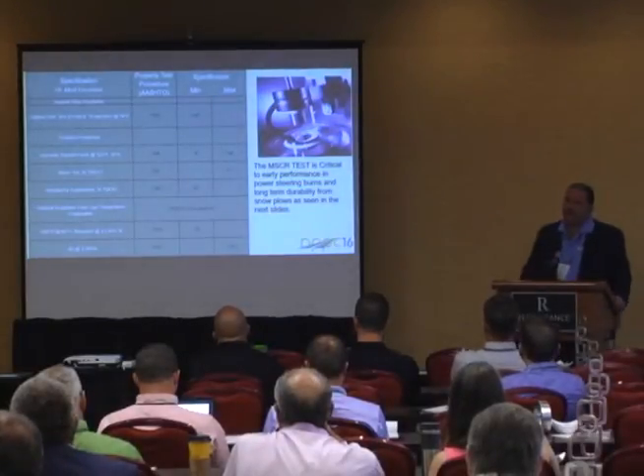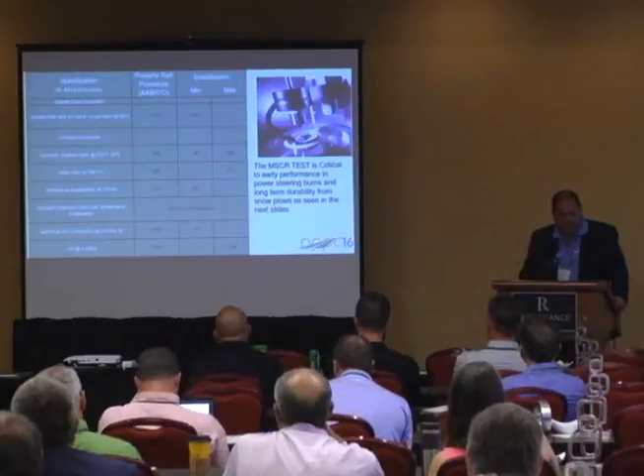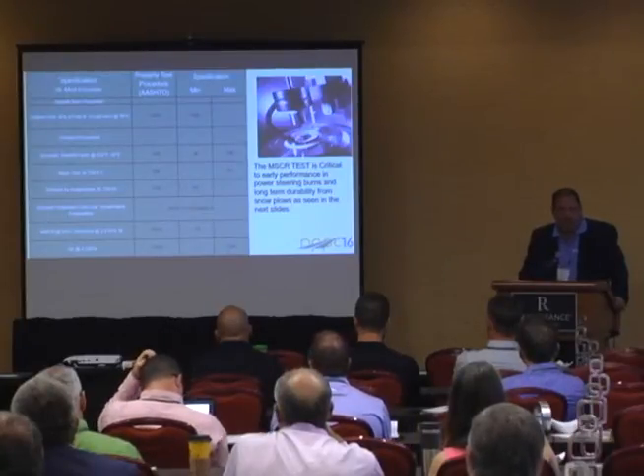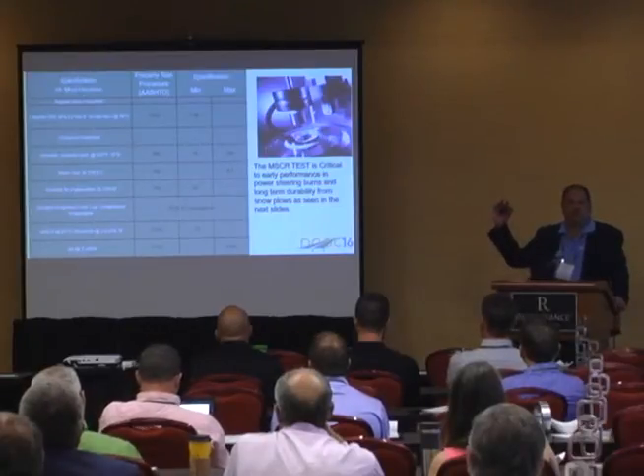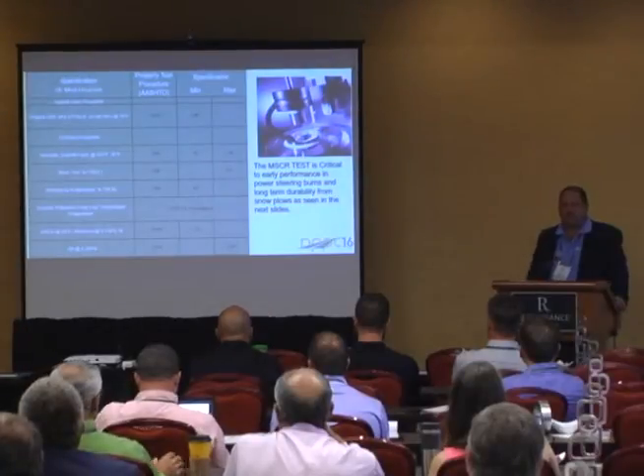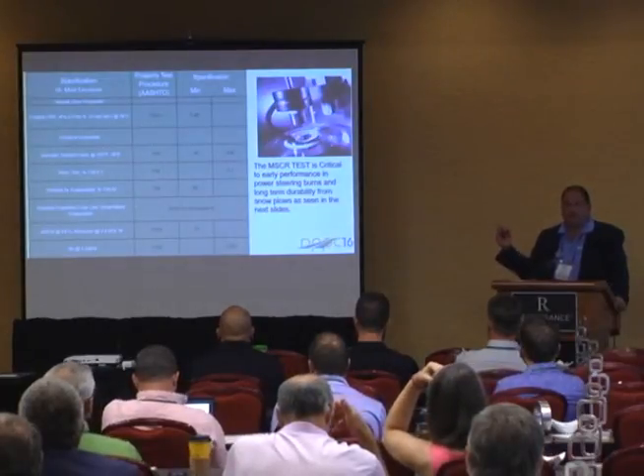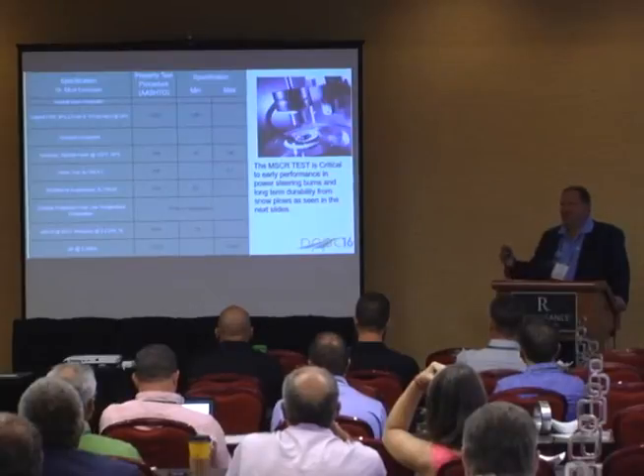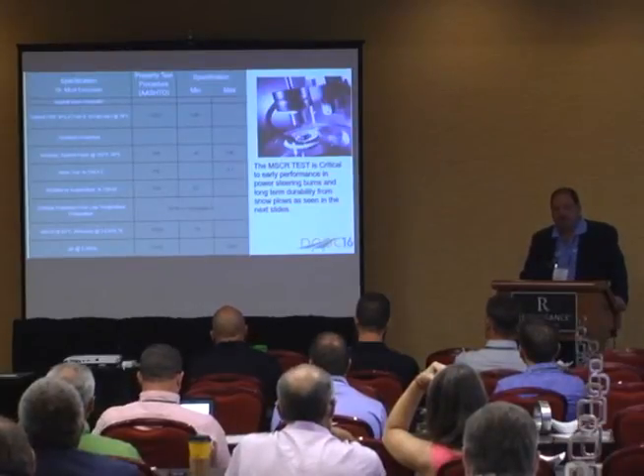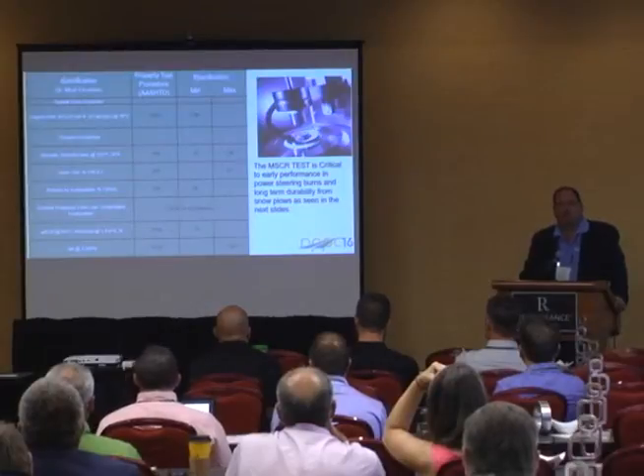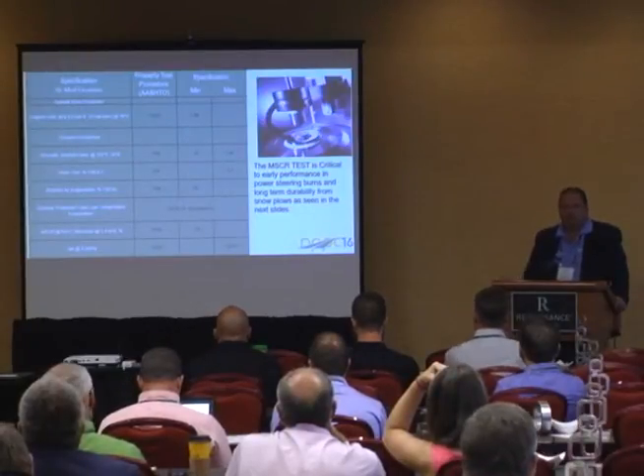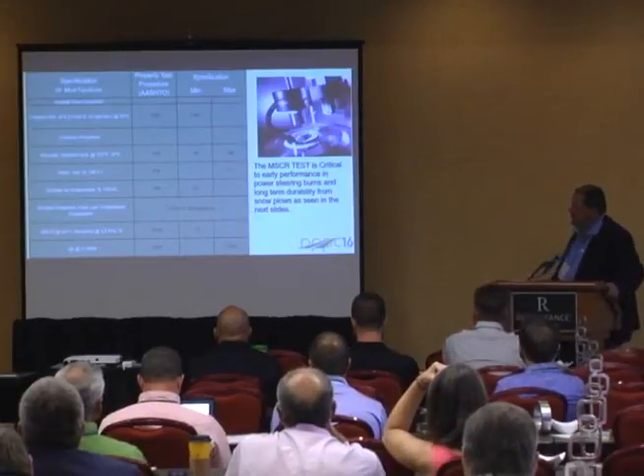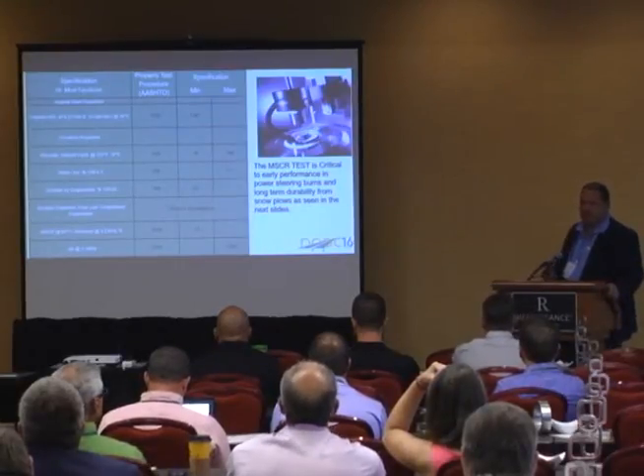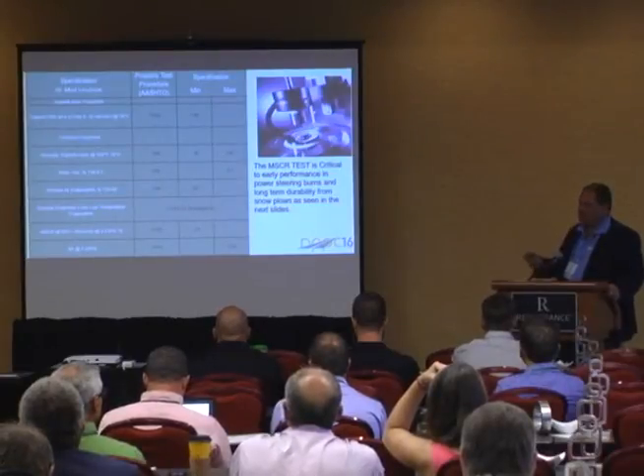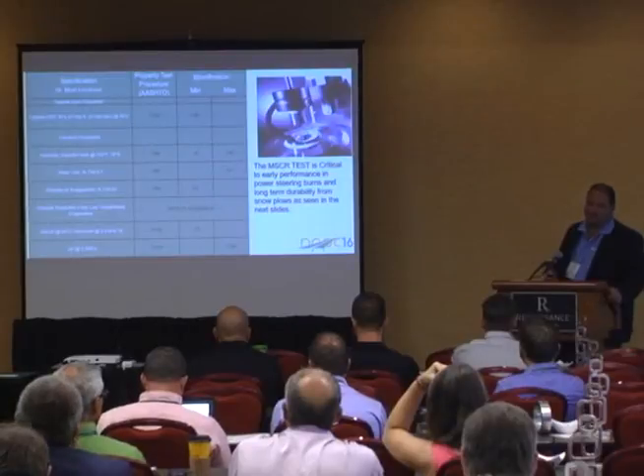So this might be a specification for the future. And this is really looking at, you look at that spec, what do most specs for emulsion have for microsurfacing or CSS? Number one would be pen. You want to know how hard it is, and that pen range would be between 40 to 90. We don't have a pen spec here. One might put a torsional recovery, a boiling point or a softening point in a specification. We don't have that in here. We do a low temperature distillation or this evaporation process, so we're not age oxidizing the pavement. So we're trying to truly mimic something that occurs in real life.